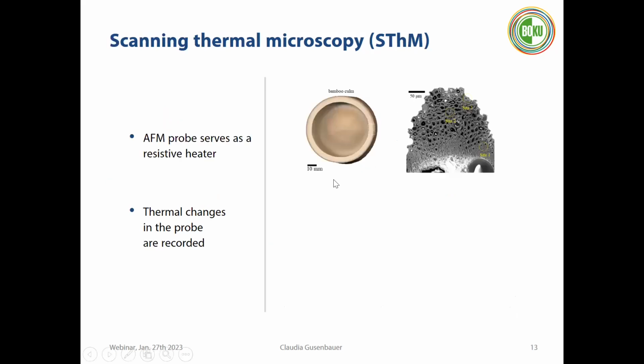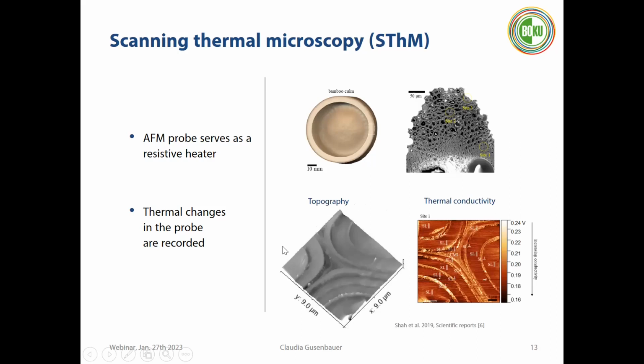And another technique that we can do with our AFM setup at our institute is scanning thermal microscopy. In this setup, the tip serves as a resistive heater, and we can measure thermal changes between the tip and our sample. For example, we performed these measurements on a bamboo cross-section. We had a bamboo sample, and we selected certain measurement positions. And then we could measure the topography of our sample.